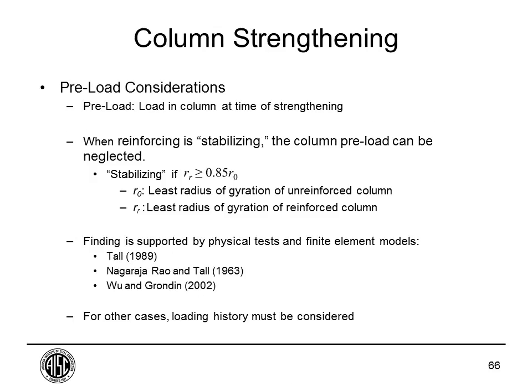And then one last thing to consider when looking at columns is the preload, which is the load in the column at the time of strengthening. So when we looked at beams, we ignored the loading history. And it turns out for columns that you can do the same thing where you ignore the load that's in the column at the time of strengthening, provided that the reinforcing is stabilizing. And what's meant by that is that the least radius of gyration of the reinforced column needs to be equal to or greater than 85% of the radius of gyration of the unreinforced column. So this finding was found through physical tests of reinforced columns and finite element models.